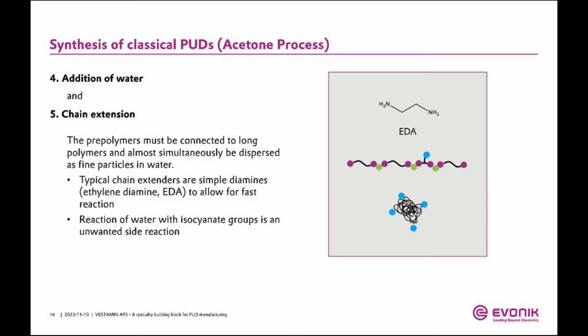So now we come to what I call steps 4 and 5. We always mention them together, and the literature debates which one you do first, number 4, the addition of water, or the chain extension, or do you do it simultaneously. For sure, you have to do it in a timely manner, close together. So now what we want to do is bring our prepolymers together, link them together with the chain extension to a long chain, and at the same time, ideally, you want to bring them into the water so that you get the smallest possible particles and the most stable dispersion.